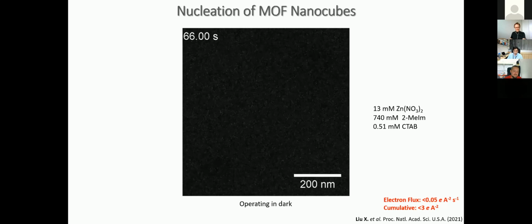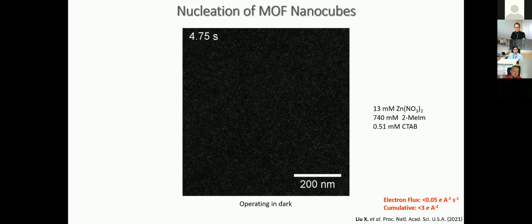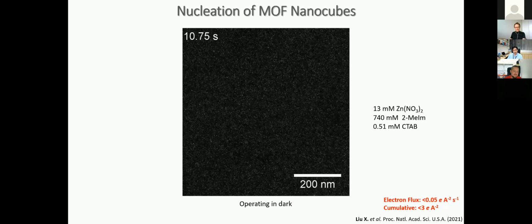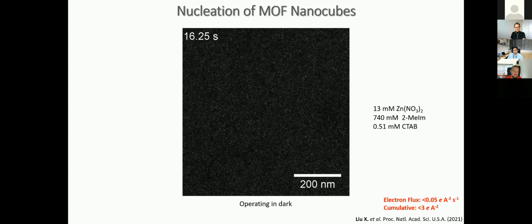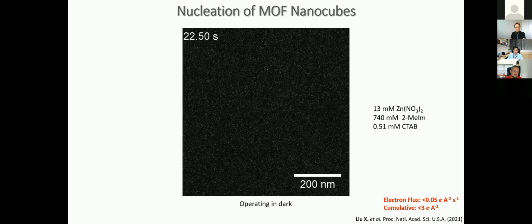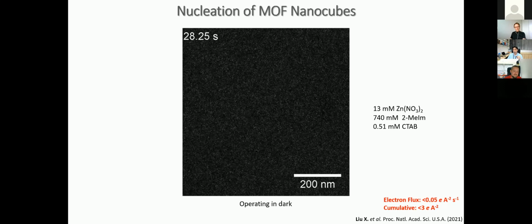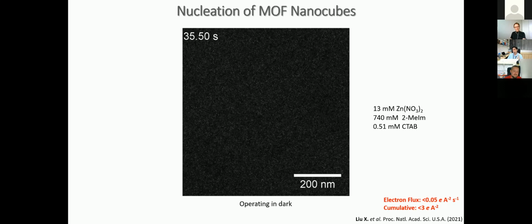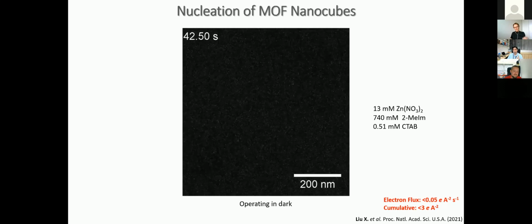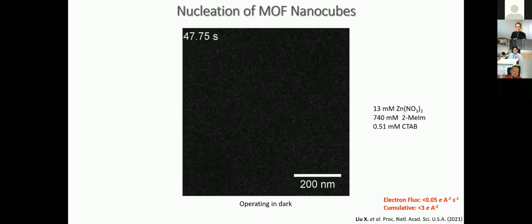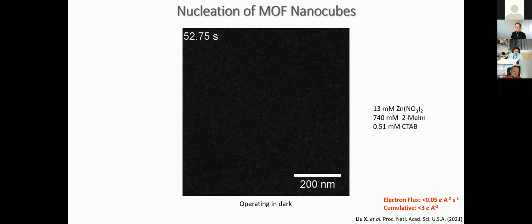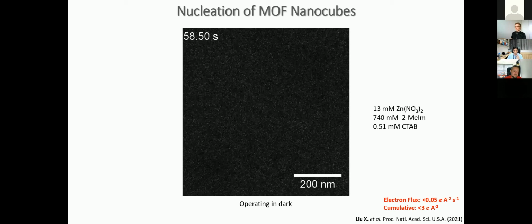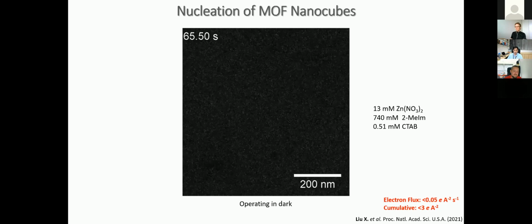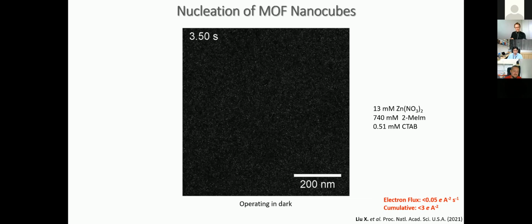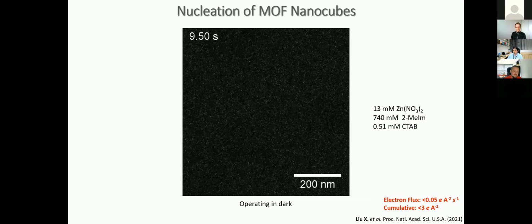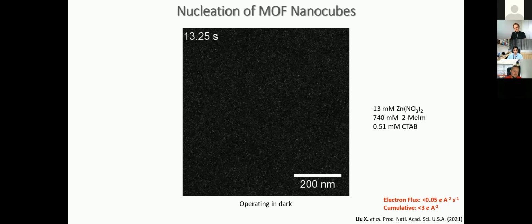So we have a precursor solution. Our electron flux is 0.05 electrons per angstrom square per second, and the cumulative dose is 3. This is much lower than the dose the cryo-EM people in biology use. They use like 10, 15, 5 in some cases. But this is well below that, right? And you're trying to do in situ. You see nothing. So that's why we do a bit of image processing, and let's see if we can see things.